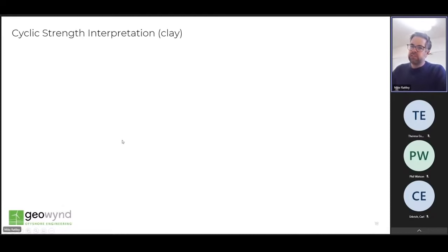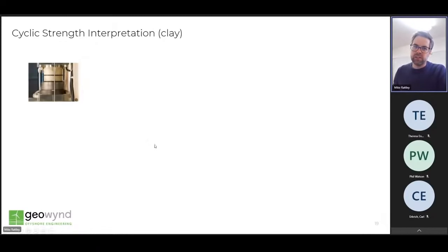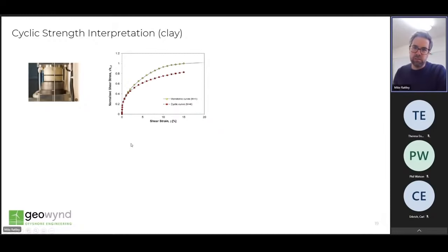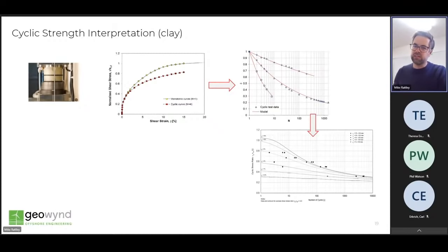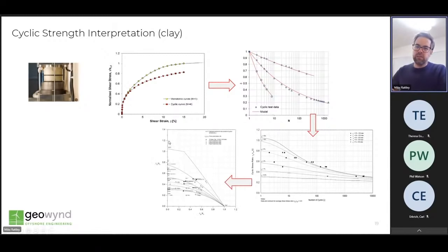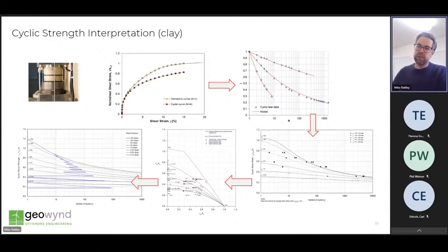So just to touch very briefly on interpretation of the tests, ultimately the laboratory test data is used to build up a cyclic response framework, which can be defined in terms of strain or excess pore water pressure, as Carl's already mentioned. The model typically starts from a monotonic response, and that's why those reference tests are important, and then can use a degradation function or a fitting technique to generate SN curves of cyclic response. And these curves indeed can be extended into a 3D framework accounting for cyclic load ratio, and then used to perform cyclic accumulation analysis to develop envelope cyclic stress strain curves. And those models can then be applied to prescribe or calibrate the representative stress strain model for numerical analysis, much in the way that Carl illustrated in his last example. This type of laboratory data set will be used to prescribe the models used in that analysis and to calibrate the response imposed on those analysis.